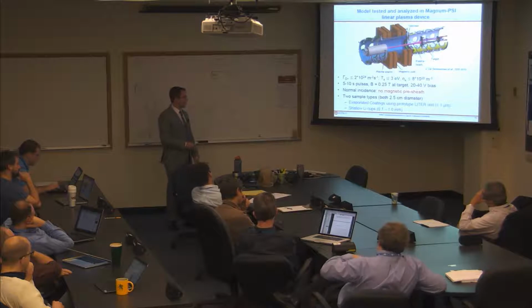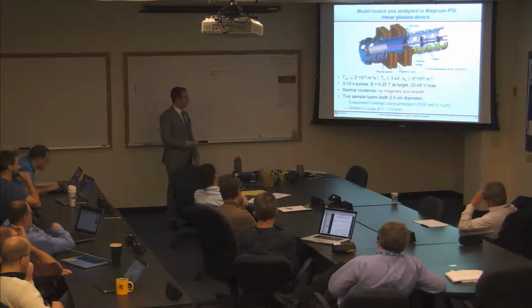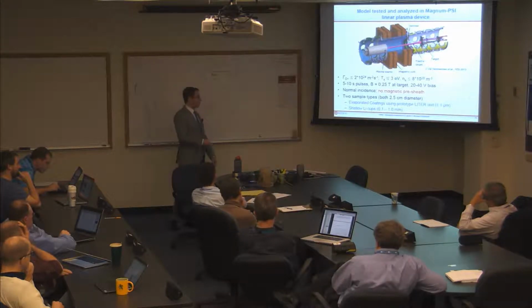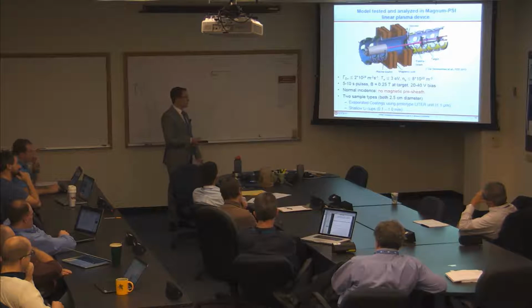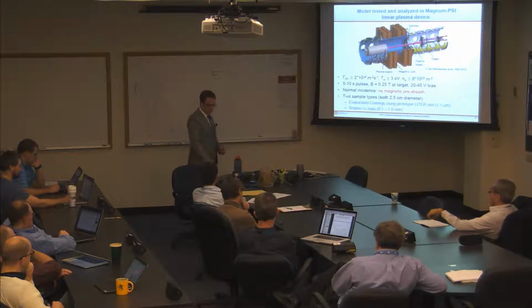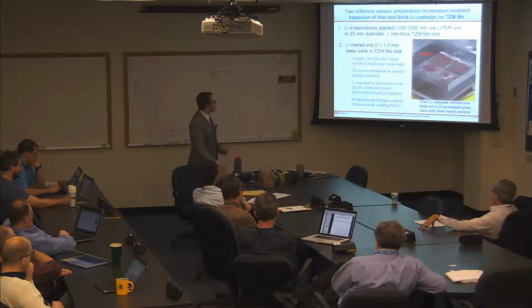And they were less than 1 micron in thickness, mostly because it would take a prohibitively long time to evaporate longer or higher thicknesses. And then to actually get thicker lithium coatings, and I'll explain why we wanted to do that, we actually preloaded lithium targets, which I'll show you more about on the next slide.